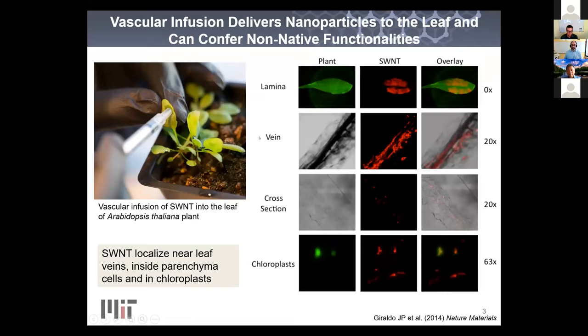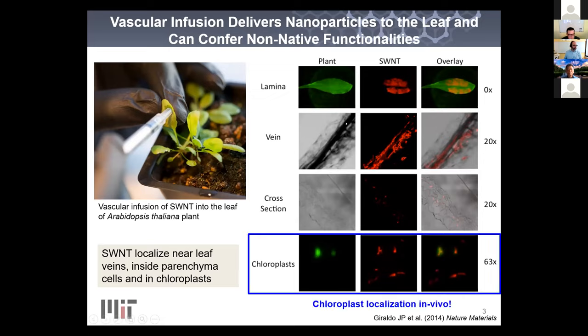The implications for plant science and agriculture are pretty significant. You can actually get this behavior to happen for nanoparticles that you just inject right into, say, the leaf lamina here. Now, this is a nanoparticle solution applied to the underside of Arabidopsis, and you can see that you fill the fluid into the mesophyll, and then if your particles have the right properties, they can actually go. You're supposed to see here that these are carbon nanotubes, and then the green is the chloroplast autofluorescence, and you can see even from outside the plant, you can park particles directly into the plant cell and even into the chloroplast.